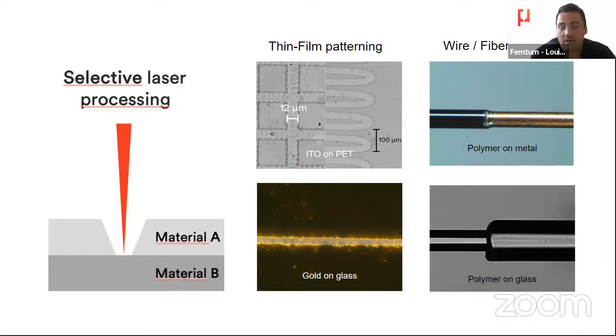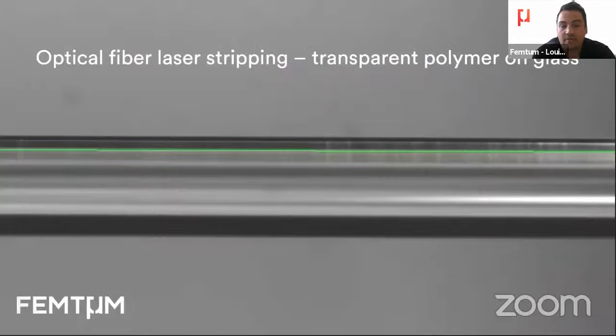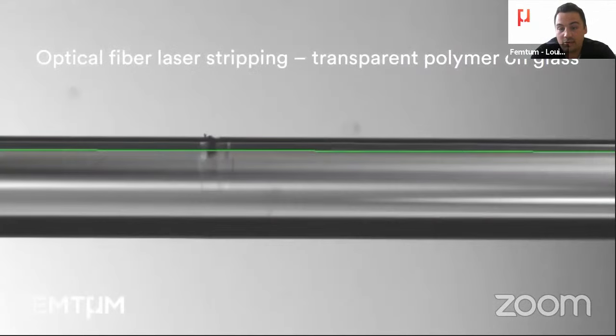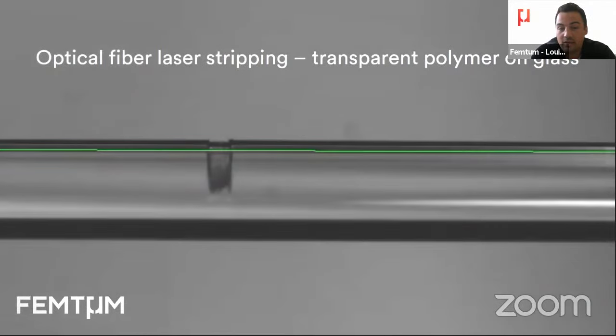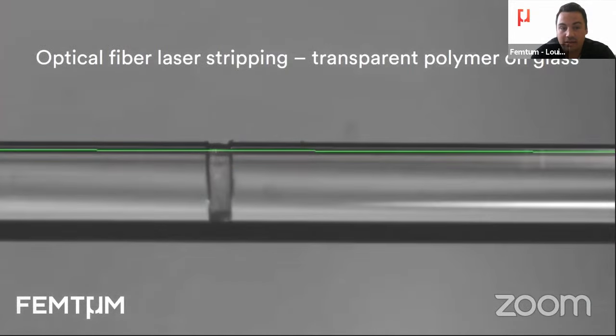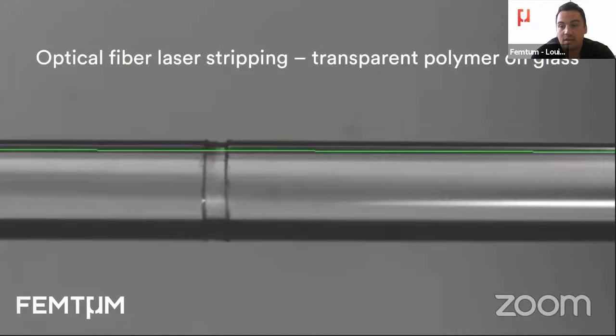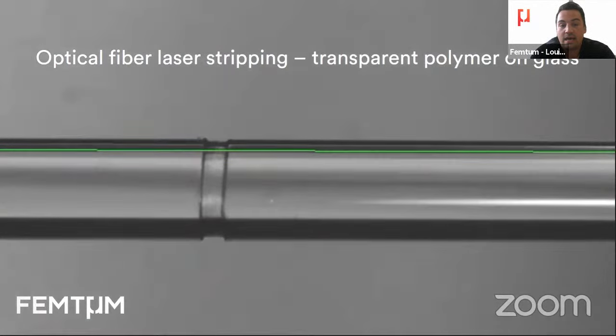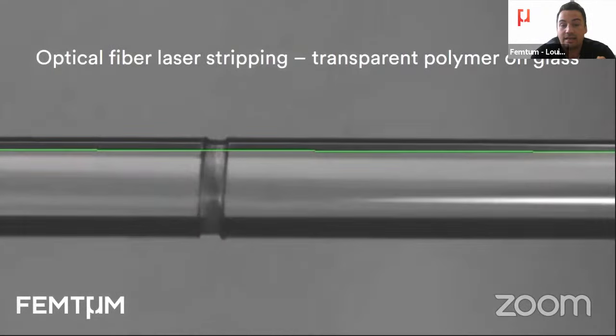And there's another set of applications in which we try to strip polymers on metal, so for wire stripping, and also polymer on glass stripping. And in this case, we have developed this process, and it's pretty difficult to find the right wavelength, the right laser to do the job because both materials are transparent in optical fibers. And what we can do at Femtum is provide you the right laser to do this job very efficiently and precisely.